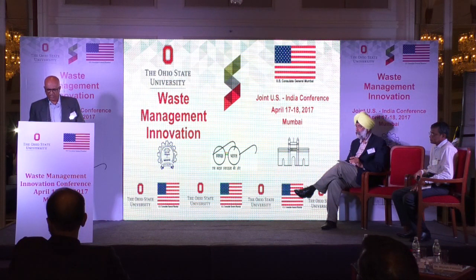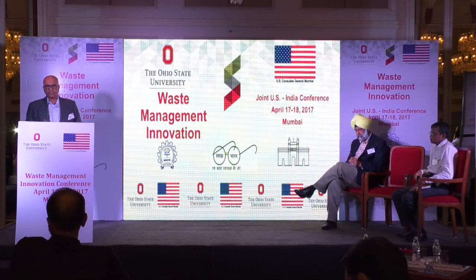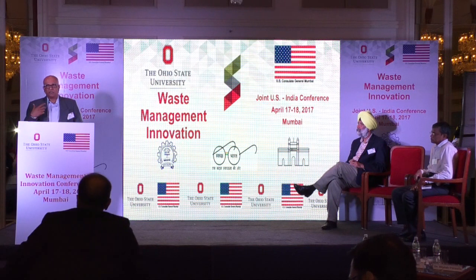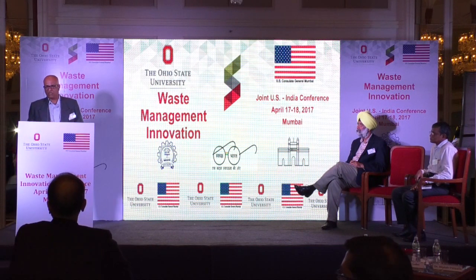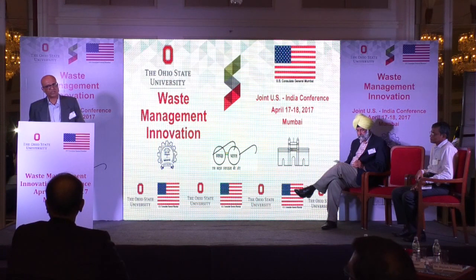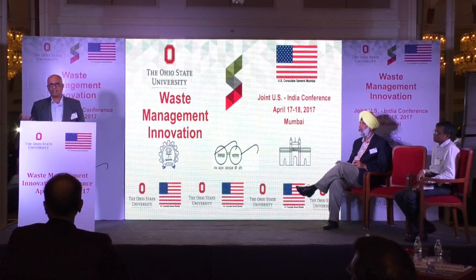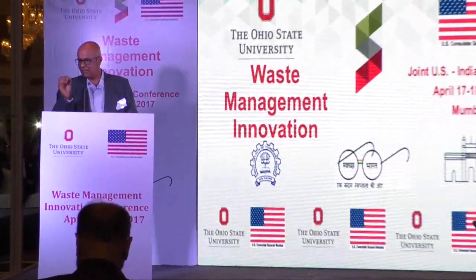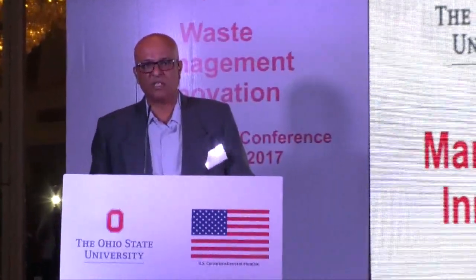There was this challenge recently about mining of sand. So we looked at making sand, artificial sand, out of fly ash, to the desired grain size. We did that, and the only problem which we faced was we had to sinter it at nearly 1000 degrees Celsius. So after making the entire sand beautiful, like mustard grains, just perfect round, the landed cost was nearly 10 times that of the sand that was coming. So we said, economically it's not working, technically it's viable.